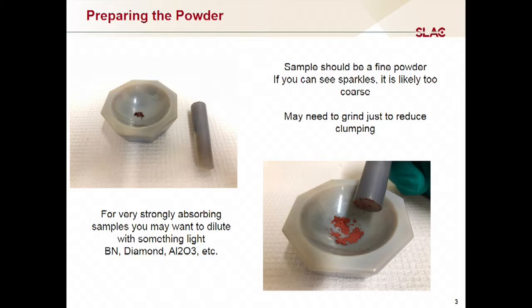And also, if your sample is something heavy, like I was saying, a heavy metal, you may want to dilute this with something light. And you have two choices. You can do something light that is amorphous, like some glass. That's not going to give you any extra diffraction peaks, but it is going to give you a constant background everywhere. That's not necessarily good. You want a low background. So what you probably actually are better off doing is adding something that is light and highly crystalline, because this will give you certain diffraction peaks, but everywhere where you don't have one of those diffraction peaks, the background is still low, and you can model whatever you dilute it with. And typically you want something of very high symmetry that leads to very few diffraction peaks. And so something like diamond powder is actually something that you might want to consider.